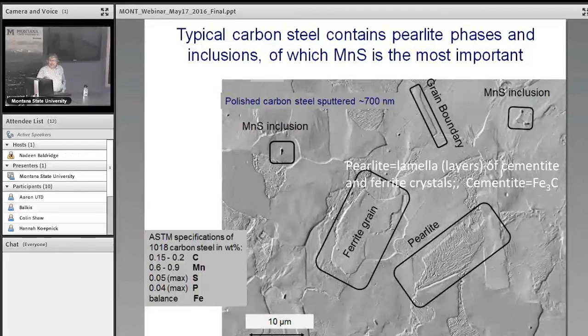When you sputter it, just bring the shiny surface into focus, what you see here is the grains of pure iron. There's carbon in it, but carbon is not inside the pure iron. Carbon is locked into what we call pearlite phases. These pearlites are made up of layers. One layer of cementite, which is iron carbide, Fe3C. Another layer is ferrite, a body-centered cubic iron. Then there's another layer; they're sub-micron thick.